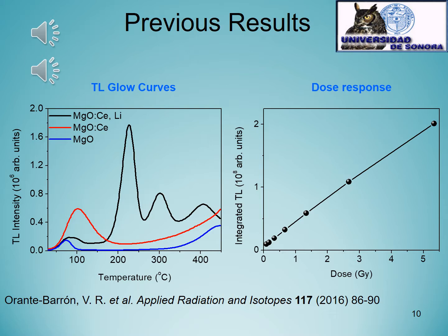For thermoluminescence results, we can observe in the graph on the left the TL Glow Curves from pure magnesium oxide, magnesium oxide cerium doped, and magnesium oxide cerium and lithium co-doped. There's a significant difference between the co-doped sample and the lanthanide-doped and pure magnesium oxide glow curves, because of different peaks located at very stable temperatures, talking about TL dosimetry. This is caused by the compensation charge effect between the lanthanide, cerium, and lithium.